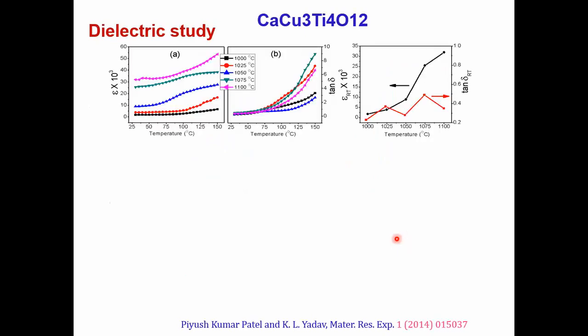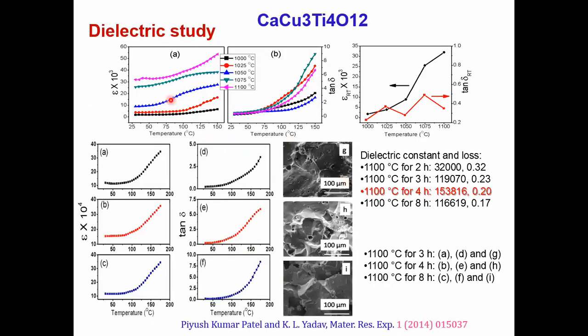Okay, so now if you compare their dielectric constant, dielectric loss, and the structure, that is at 1100 degrees for 3 hours, 4 hours, and 8 hours. This is 3 hours, this is 4 hours, and this is 8 hours. How the dielectric constant has increased is plotted here, so we have got a better value for 4 hours.